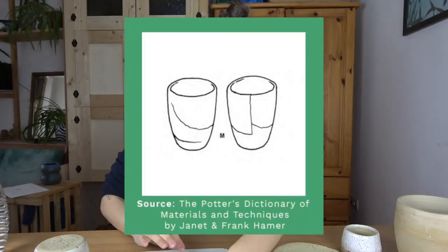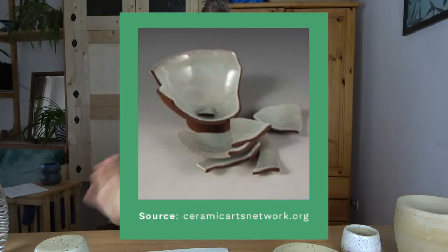End crack. I've seen this a lot with my friend who likes to glaze only the inside of her pots. This is basically a fitting issue between the glaze and the pot. Imagine this pot is glazed only on the inside — the glaze is going to be pulling at the walls, wanting to shrink them with it. If your walls aren't sufficiently strong — thick and well made — they could easily shatter inward with this shattering effect. If you only want to glaze the inside, make sure your walls are well made and a little bit thicker. You can also try a different glaze — maybe that glaze just isn't fitting well to the body of your pot.